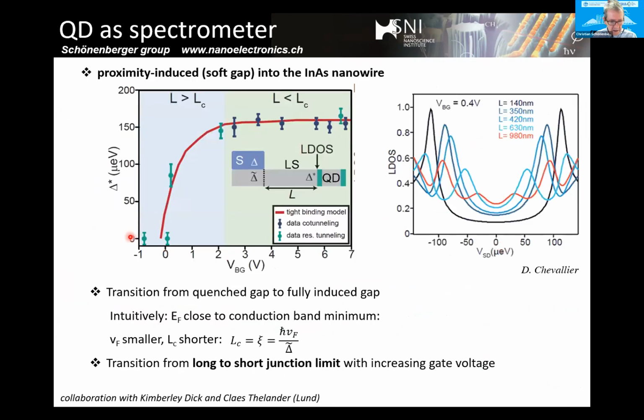Okay, so the interesting thing is that the gap appears at some threshold. Maybe you see first, in proximity, a bit smaller gap, but then it goes up very quickly and stays essentially constant. And the way we interpreted this transition, from a gap which is opening, with Andreev bound states that are smaller than the gap, is by saying that on the left side the length of the wire, the length of the lead, is longer than the coherence length, and so you are in a long junction limit here, while on this side you change into the short junction limit.